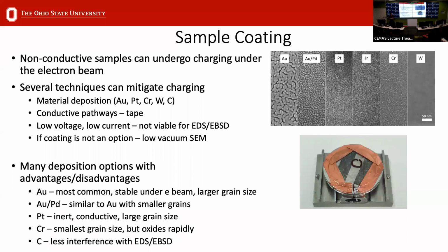So, sample coating. Typically for metals, you really don't have an issue with your samples being conductive in the electron microscope. But as you move into materials like ceramics, or in some cases when you mount your samples in epoxy, that might be non-conductive. That could cause some issues in the electron microscope, especially if you're using high voltages and beam currents. It could have a difficult time dissipating that charge.